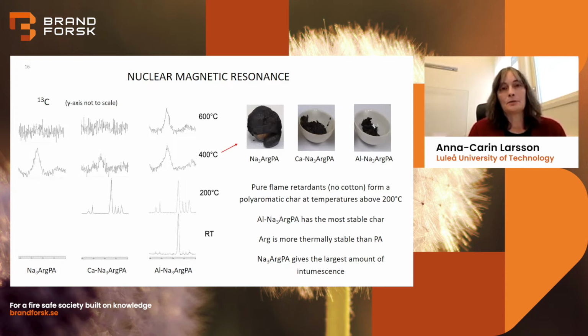We can see that those gases that form when the phytic acid and arginine are breaking down between 200 and 400 degrees can intumesce the char that is forming. So you can see the figures there, photos of the flame retardant at 400 degrees from the furnace. There is an increase in volume, especially for the sodium version, but also when calcium and aluminium are added to the system, we can see a volume increase compared to the original sample.